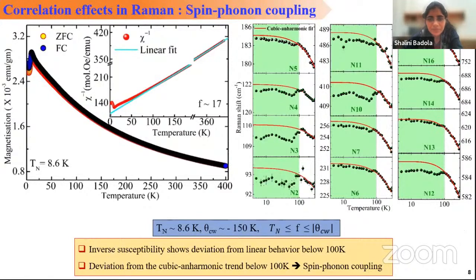Yes. Here what I see is that for some of the modes, the fitting is quite good compared to the rest. Do you have an explanation for that? For example, the N5 or the N16 one? Okay, ma'am. So N5, you mean this red curve. Yeah. So actually, this red curve is what the phonon is expected to follow. What is happening below 100 Kelvin is that these data points are deviating from this expected trend. That's what I can see, but N5 and N16 are deviating less as compared to, say, N3 or N2. Do we have some understanding of that?